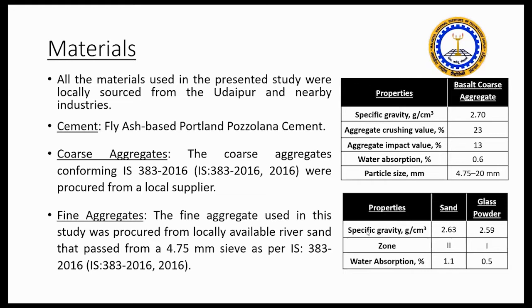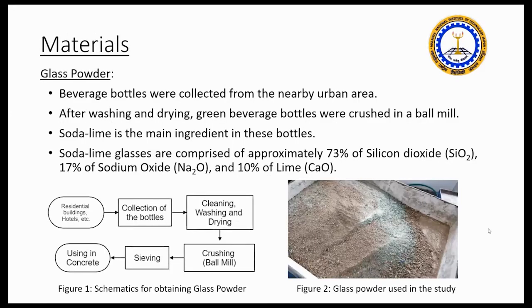The fine aggregates used in this study were procured from locally available river sand that passed through a 4.75 mm sieve, which conforms to IS 383:2016. Similarly, you can see that there is glass powder also, and the specific gravity of sand and glass powder are almost the same. This is the glass powder.